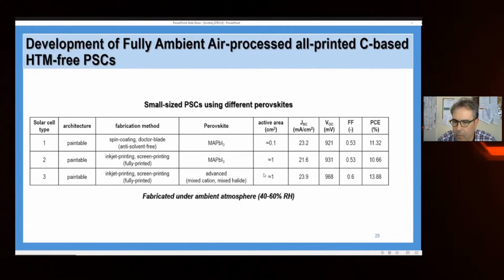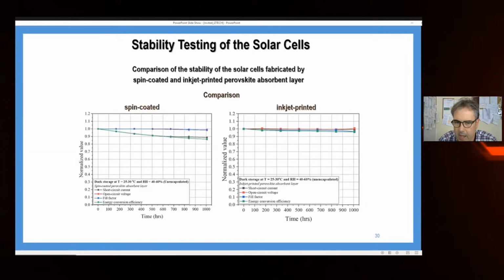We have developed a 1 centimeter square device with the inkjet print technique with around 14% efficiency, which is very good and very high for this technology. And we also have very negligible hysteretic behavior for these devices. I want to skip a little bit now. Here I can show you, of course, that we also have better stability for this device made with inkjet printing than the spin-coated method.